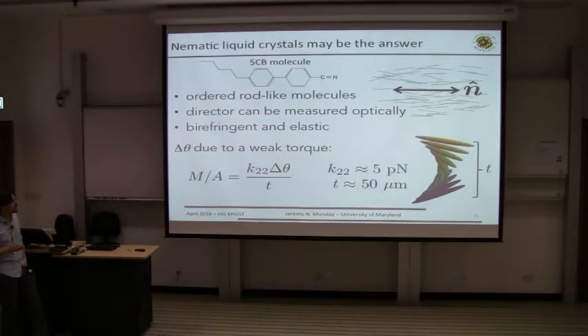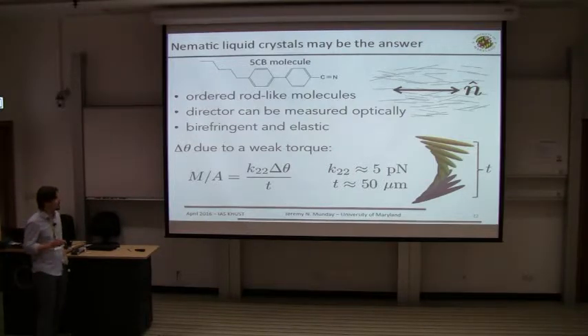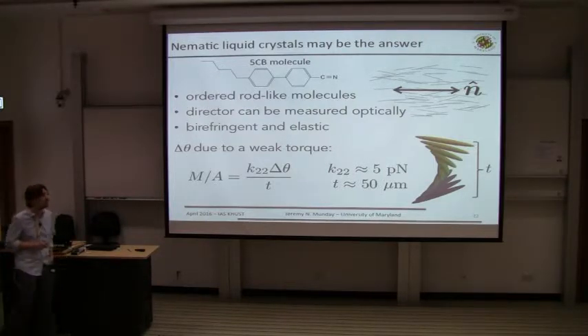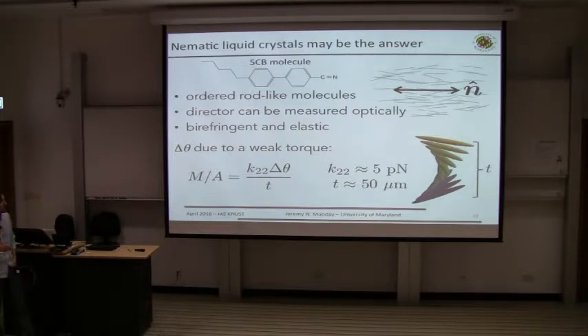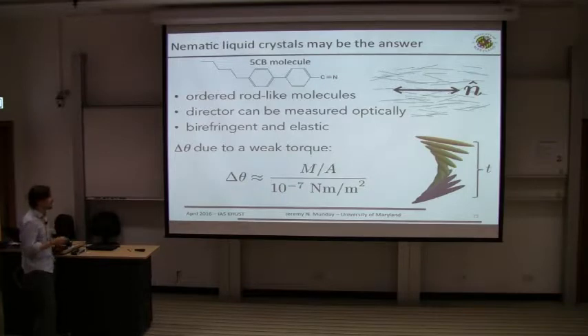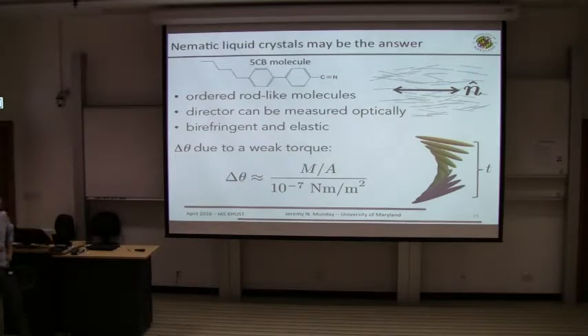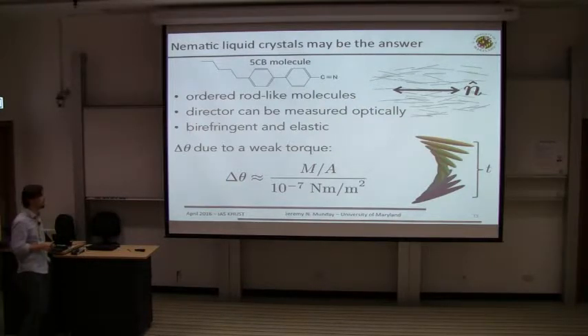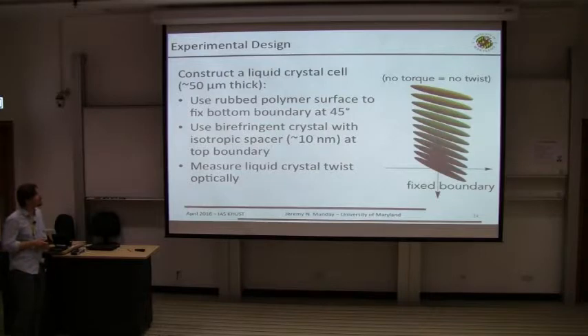And so for a common liquid crystal like 5CB, this constant here is something around 5 piconewtons. And so if you pick a thickness of your liquid crystal of about 50 microns, you get this relationship between the angle that you'd measure and any torque that might exist to do the rotation.